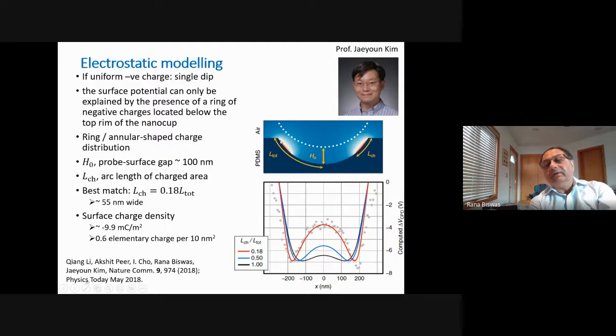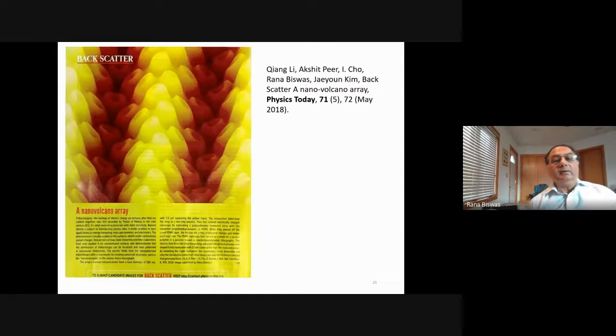However, if you put the charge in a smaller region, right at the rim of the nanocup, so it sort of forms an annular ring-shaped structure, then you get the surface potential in red. So you see it tracks very nicely with the experimental measurement. So you see you have about a 50 nanometer wide ring and the surface charge density of about 9 millicoulombs per square meter. And it's less than 1 elementary charge per 10 nanometer square. So these are very strongly charged structures that result from the frictional stress in the nanocup during the demolding.